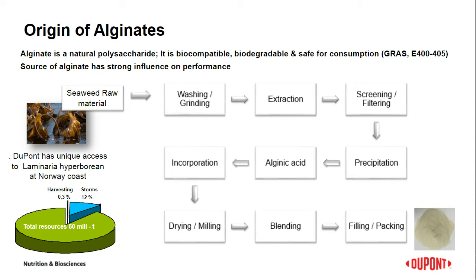In the seaweed, the alginate is mainly present as calcium salt. So the first part of the process is to convert the insoluble calcium derivative into a soluble form, which is described as the extraction process, which is performed with high pH aqueous solutions. The dissolved alginate must now be separated from the seaweed residuals, which is mainly cellulose. The residual is usually slimy and it is removed by a filtration process.